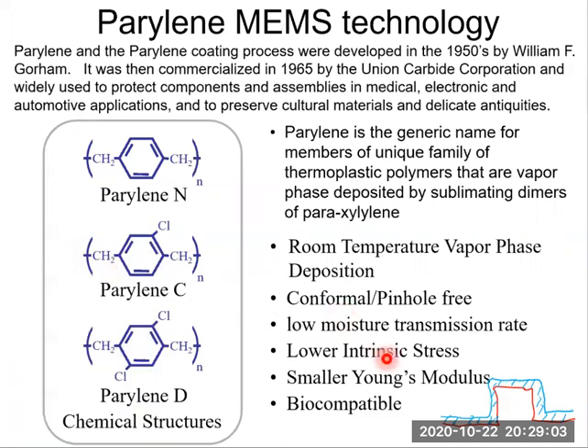Parylene, especially parylene C, has a low moisture transmission rate, so sometimes it can be used as a waterproof barrier. It also has a lower intrinsic stress and smaller Young's modulus. It's a polymer, so its Young's modulus is much smaller than that of solid state materials such as polysilicon or silicon nitride. And parylene is biocompatible, so it has been used to coat medical devices or medical implants. It's biocompatible.